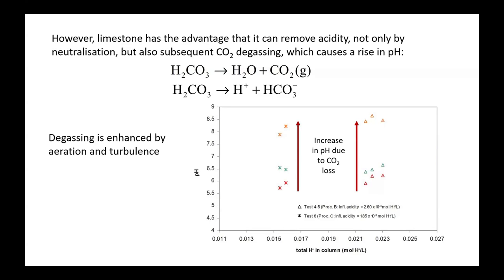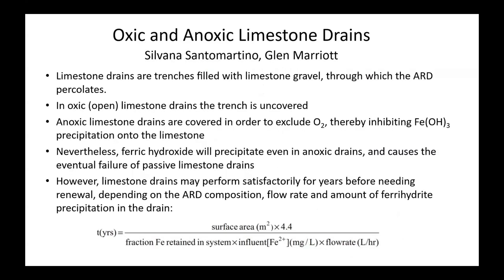CO2 is my favourite gas, but I don't want to get sidetracked. So Silvana Santamartino, one of my PhD students, worked on limestone drains, and she showed a few interesting things about them. There's two ways that they're used, either open drains, which I showed a photo of before, or closed drains, where you dig a trench, fill it with limestone, cover it over, and allow the acid rock drainage to percolate through it. The idea of covering it is to exclude oxygen, so you stop the oxidation of Fe2+ to Fe3+, and therefore inhibit the ferric hydroxide precipitation.